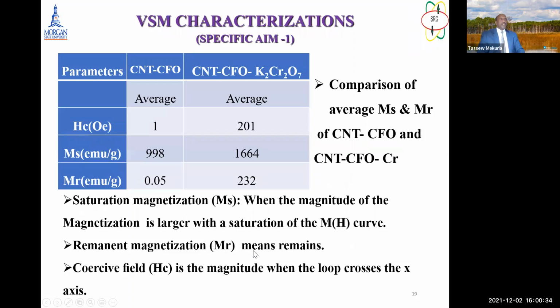Okay, so we get the result. The coercive field is the magnitude where the loops cross the x-axis, as you know, and we take the average. For CNT CFO we have 1, and for CNT CFO with potassium it increases significantly. And Ms, in electromagnetic units per gram, is the saturation magnetization, and it also shows a significant increment. And Mr, the remnant magnetization, which is before crossing the x-axis, also shows a significant increment. So we compare that without and with chromium.